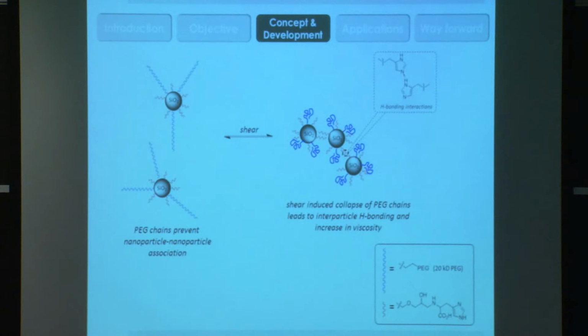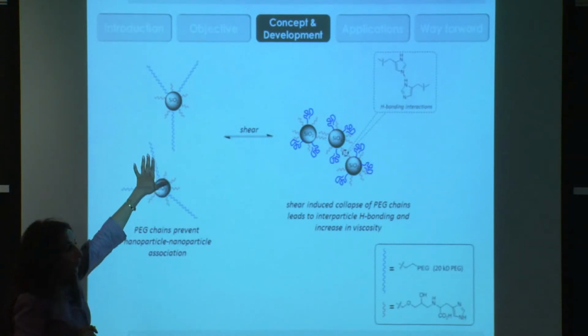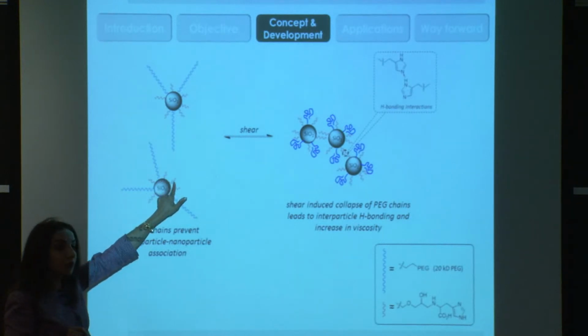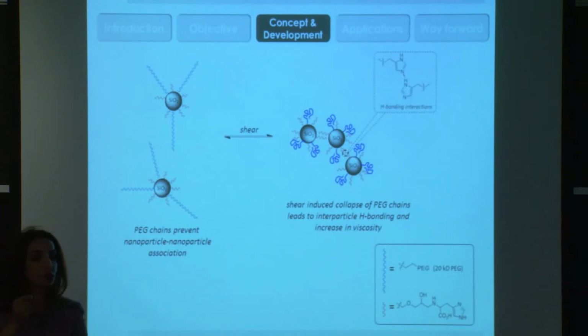So this is a brief about the chemistry of how we synthesize this material. The silica nanoparticles are functionalized with two kinds of polymer, one with a long chain and the other with a short chain. The long chain will be left free, and the short chain will be functionalized with a specific functional group using materials like histidine. And why histidine? Because histidine has the ability to form very strong hydrogen bonds that will be stable.